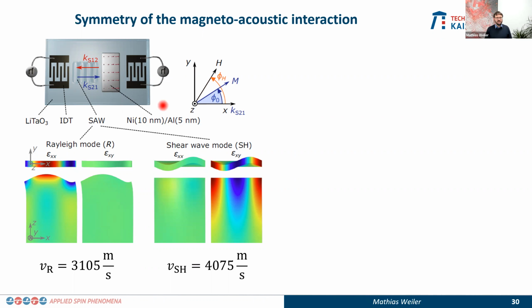Okay? So we had already looked at the Rayleigh mode. Here the substrate is lithium tantalate, and that supports a well-known Rayleigh mode with a sound velocity of about 3,000 meters per second. But it also allows for a horizontal shear wave mode. Okay? The horizontal shear wave mode means it's a wave that basically propagates like this. It's a pure or almost pure shear wave, as shown here in our COMSOL simulations.